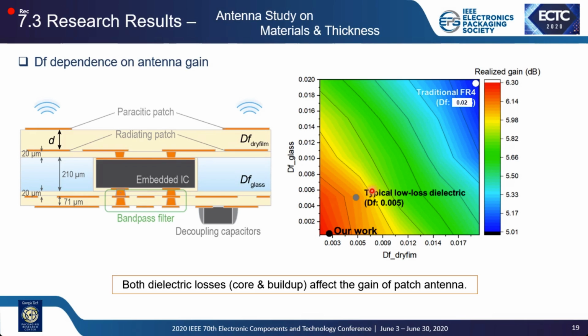But if you use pretty low DF materials for both glass and dry film, we can get a very nice realized gain. So both dielectric losses affect the gain of the patch antenna a lot. So that's the main reason why we need low loss materials for antenna integrated packages.